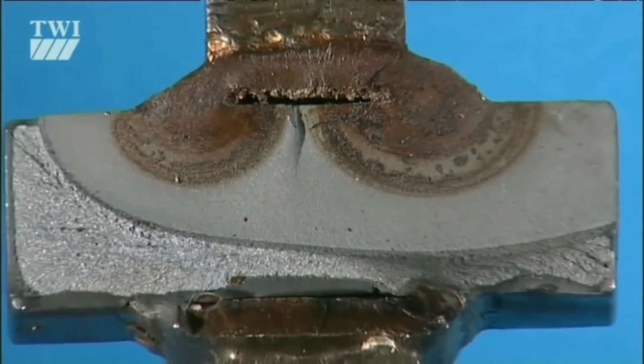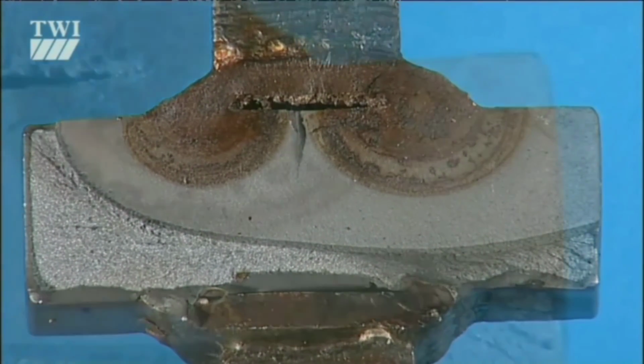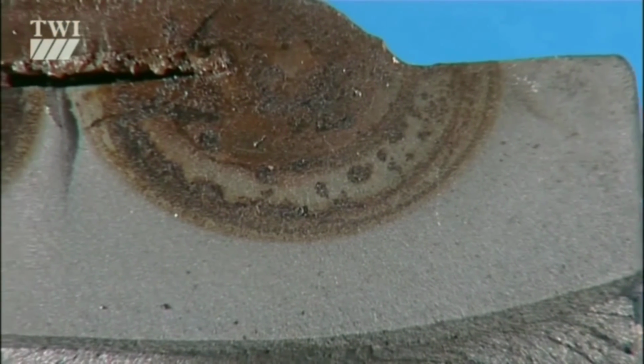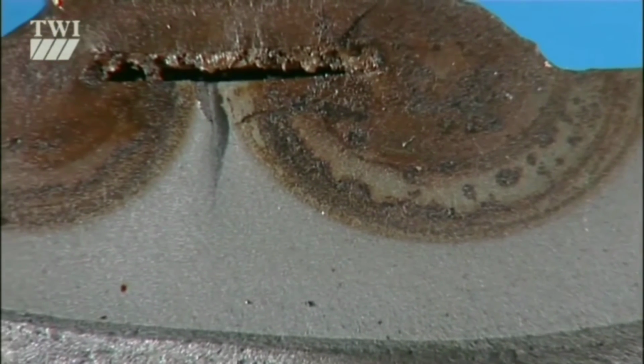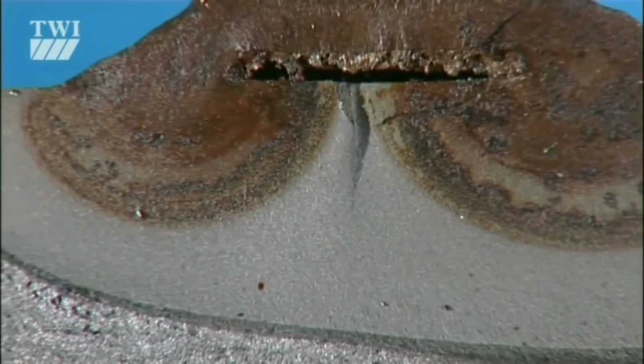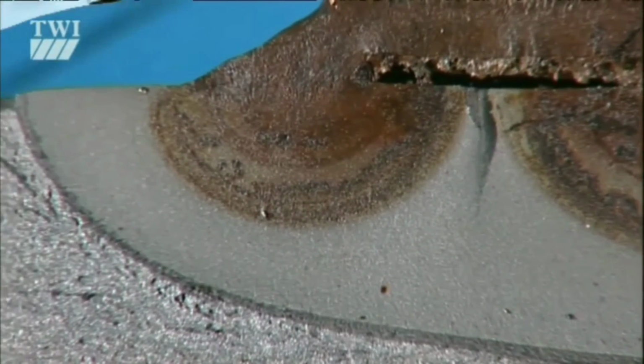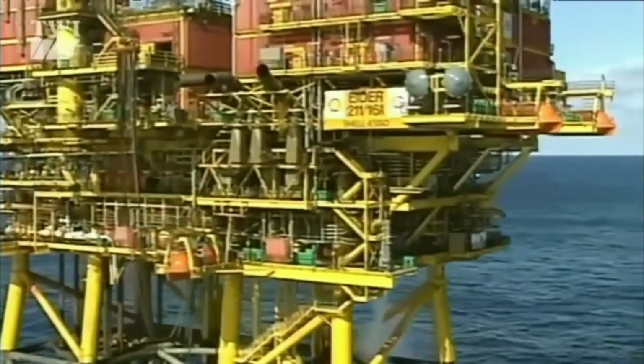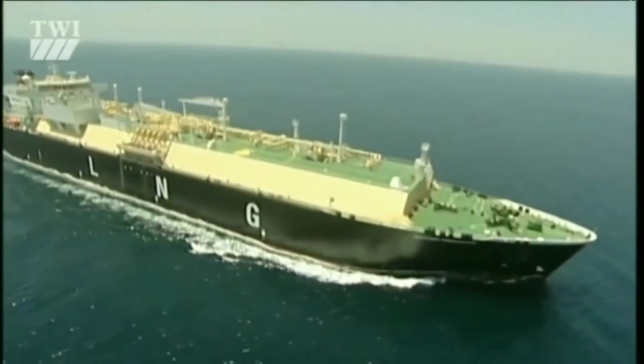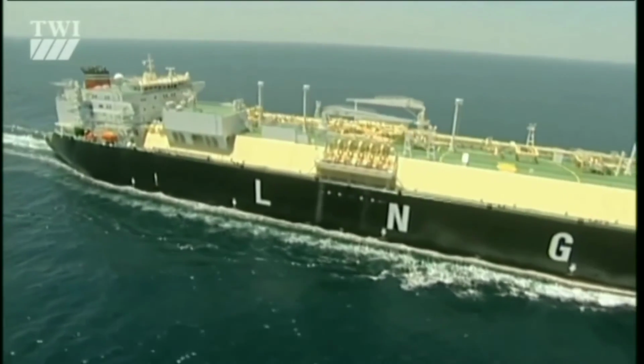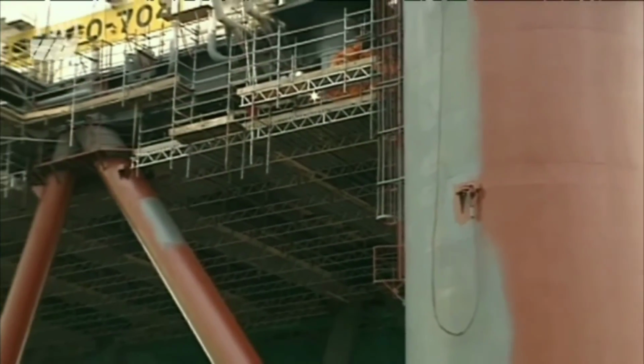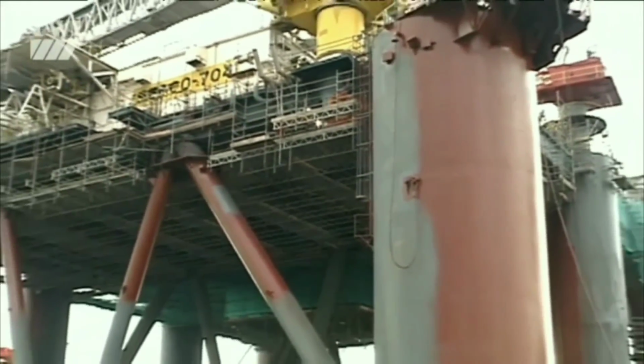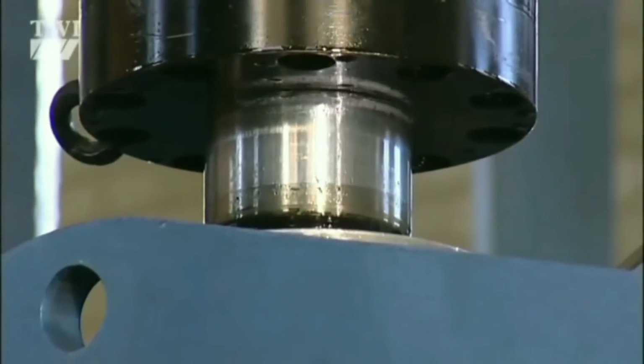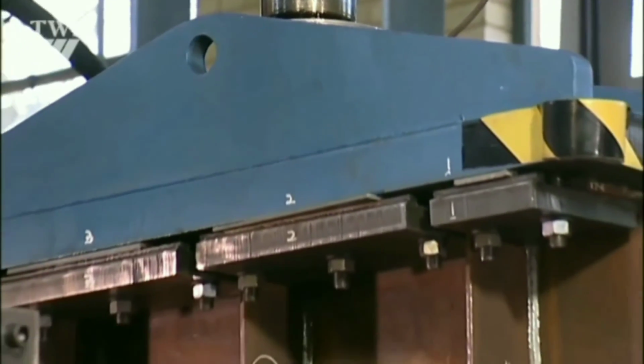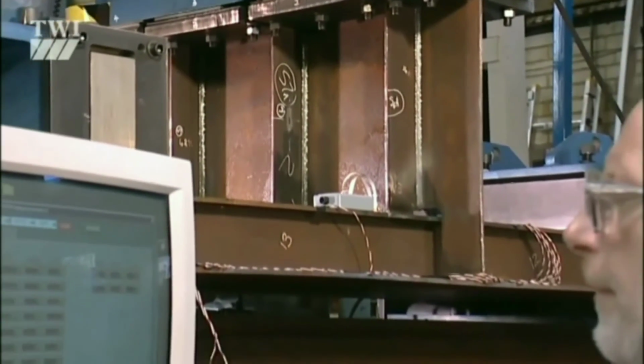Fatigue crack surfaces have a distinct look about them. A smooth appearance around the point of initiation and well-defined steps corresponding to the last few cycles just before fracture. In practice, a degree of redundancy is often present in engineered structures. So, a redistribution of stress takes place, and the propagation of a crack may be slowed down or even halted. There's no danger of collapse, but the structure's stiffness may have deteriorated to an unacceptable level.